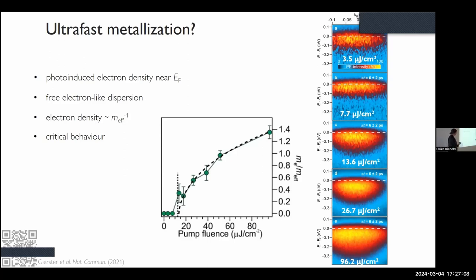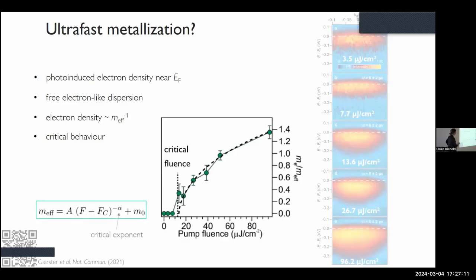And the critical density, the critical fluence is 13.6 microjoules per square centimeter. And here I learned that this is not your exact field of interest. This is like a factor of 1,000 smaller than usual photo-induced phase transitions. Normally you are in the millijoule range here, and this is quite remarkable. And this also leads to